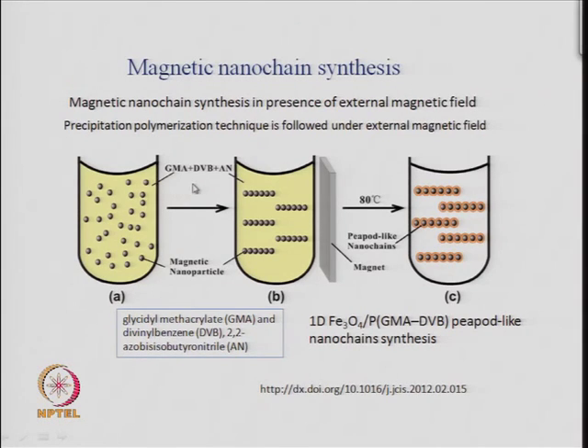So, you have this, and then you add them together with the magnetic nanoparticles and you apply a magnetic field. So, you bring a magnet close to each. So, the magnet will align these particles, and once they are aligned, the monomers of this mixture of three will polymerize. So, you have a precipitation polymerization technique. So, you want them to polymerize, and this polymerizes at around 80°C. So, in the presence of the magnet, these particles are made into chains. Then the polymerization occurs, and when the polymerization occurs, they form this kind of pea pod like nano chains. Pea pod means you have those peas with their cover, and they form a well defined cover on top of these particles. So, this is a methodology for synthesis of nano chains.